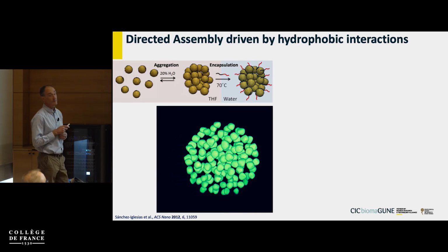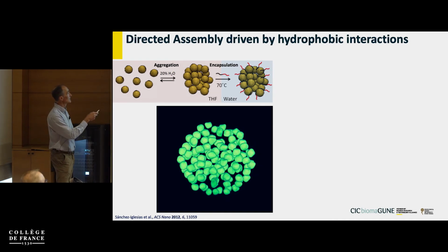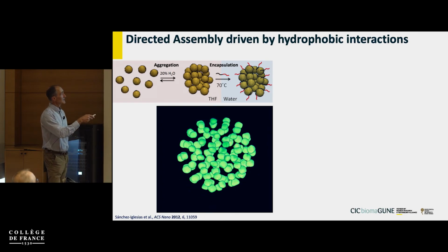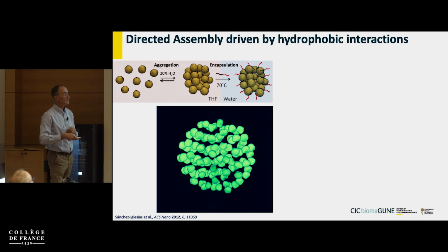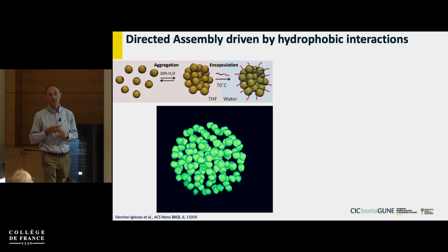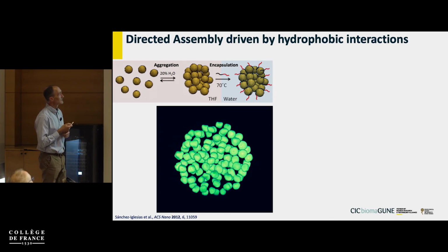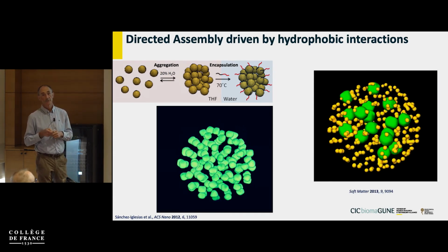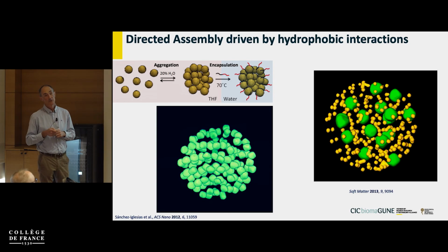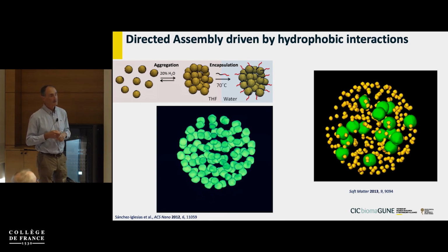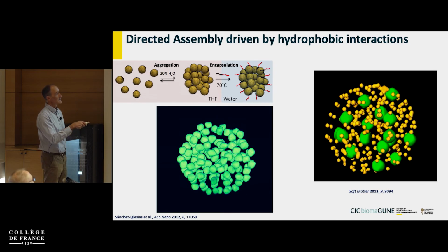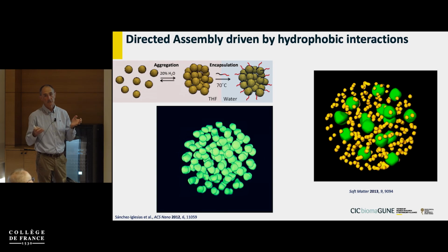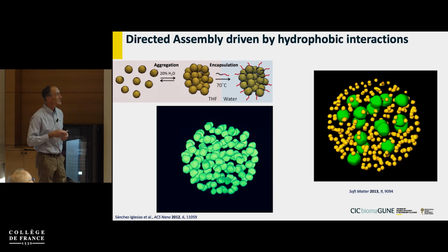You remember this from last week. So we were using hydrophobic gold nanoparticles coated with polystyrene, encapsulating them in a block of polymer, and then obtaining very well-defined three-dimensional arrays of the particles. Now, what I didn't show you is that this can also be done with mixtures of sizes, so you can co-encapsulate big and small particles, which was not really obvious at the very beginning. But obviously, the particles were stable enough that they were completely mixed in the solution, and so they were co-aggregating very nicely.